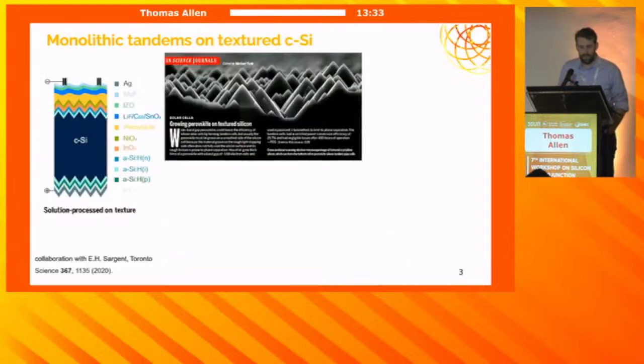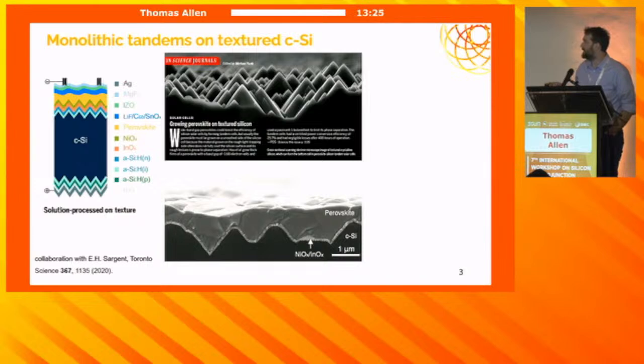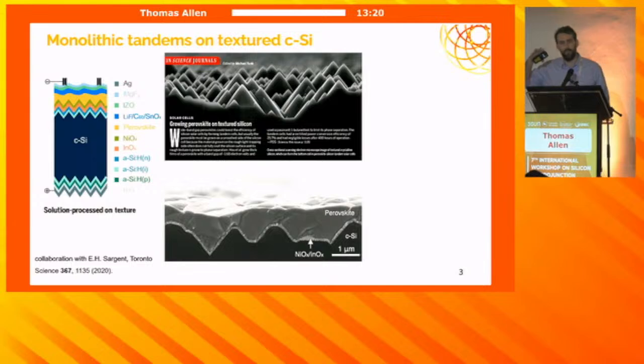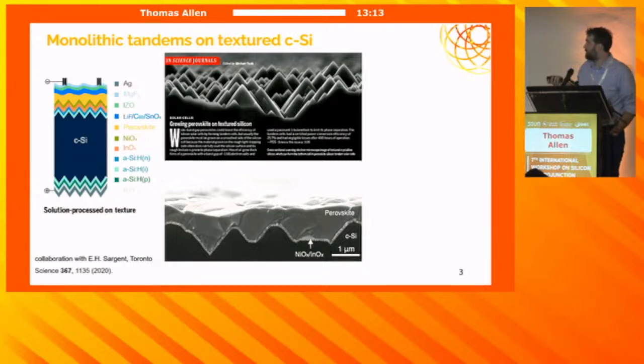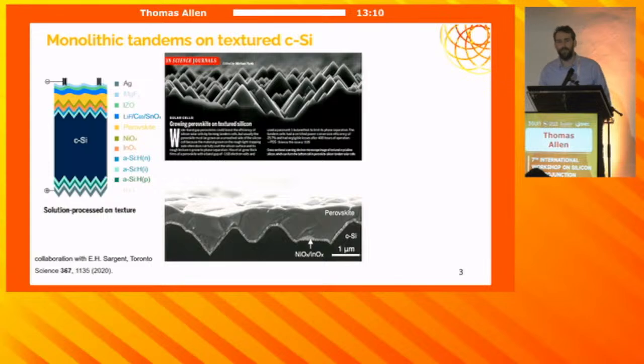So you can see the kind of process here. We started in 2020 with a really great collaboration with the University of Toronto. And here you can see the cross-section of the device showing the top cell. The perovskite is such a significant concentration that it's quite thick and fills up the spaces between the pyramid texturing, which has been reduced down to about 1 micron in size. That gives us sufficient optical reflection suppression of the front reflection, and also decent light trapping as well.